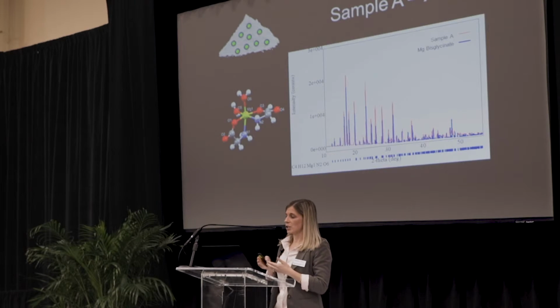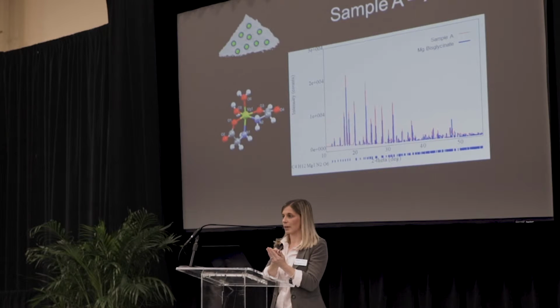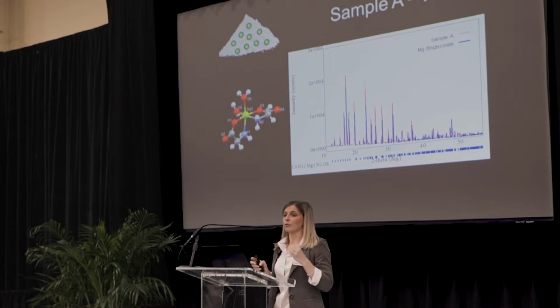So the red data is showing you sample A, the fingerprint for sample A. The blue data is showing you the fingerprint for this chelated magnesium bisglycinate. And what you can see is for every point there's red data, there's blue data overlapping it. So these are indeed the same product, and sample A is fully chelated.